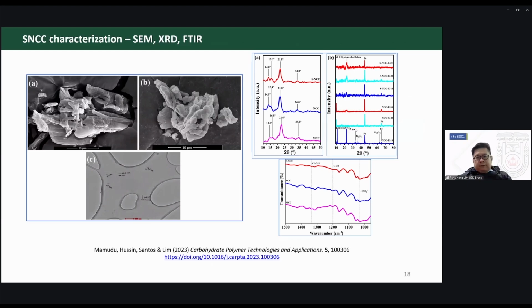Here we have the SEM images of our nanocellulose. On the left is the normal nanocellulose, and on the right is the sulfated one. The sulfated one looks smaller but also has more porous areas in it. That's not surprising, because to make this sulfated nanocellulose we put it through more acid hydrolysis than the normal nanocellulose. So even though they all start from the same feedstock, this has an additional step, so we're not surprised that the particle becomes smaller and has more porous areas.